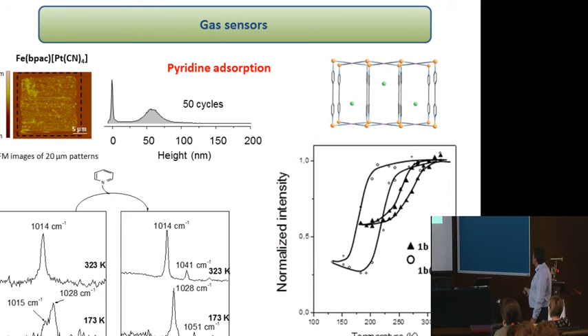Okay, just very fast, we have also demonstrated that using these patterns, it's possible to have the gas sensor effect. Like before for the powder, you have the same effect for the inclusion of pyridine. So you have, again, the increase of the active species and the modification of temperature transition.